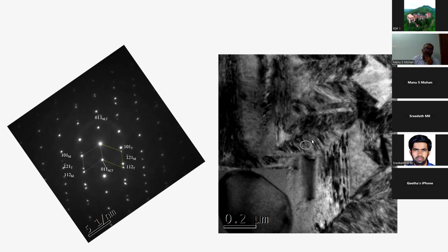and know whether the material will withstand this much load. But a metallurgist, on the contrary, might be interested in whether my nature of twinning will contribute to this strength. For example, this type of twins will influence the mechanical properties. For example, I need 2% shape recovery, 2% strain, complete recovery. Whether, if I have this twin, I will get this recovery or not, that is my question. So I was worried about that, and therefore I have taken that.